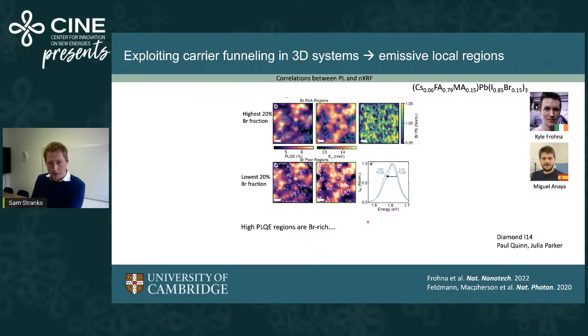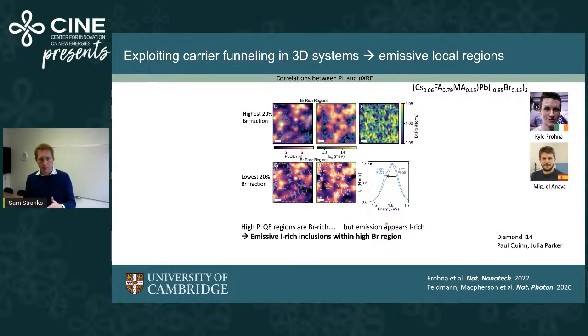And so we reconcile this by the fact that these measurements of the bromine fraction are a bulk measurement. So what it's saying is that the overall grain itself is slightly more bromine-rich. But what we have evidence for is that there are small iodine-rich inclusions within these more bromine-rich grains, and that's where a lot of the recombination happens. So carriers funnel down onto these low gap iodine-rich inclusions and then recombine with very high relative efficiency. And that's why we're seeing high PLQE in these regions.